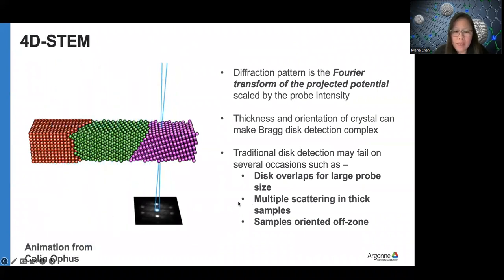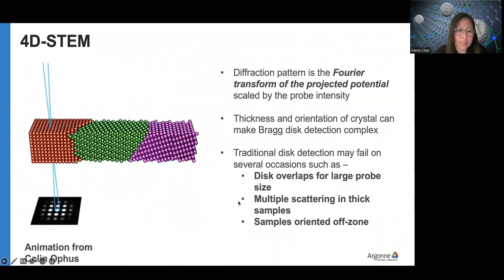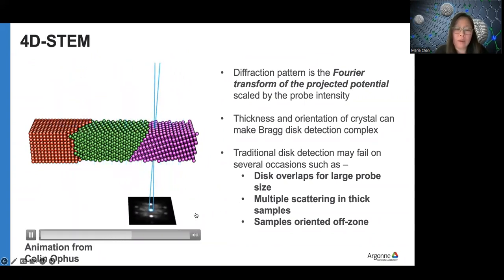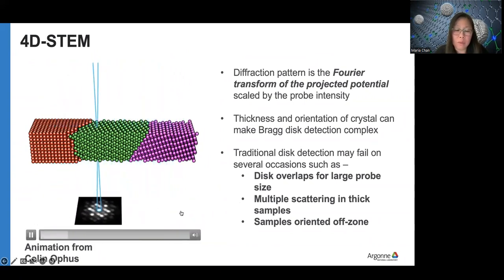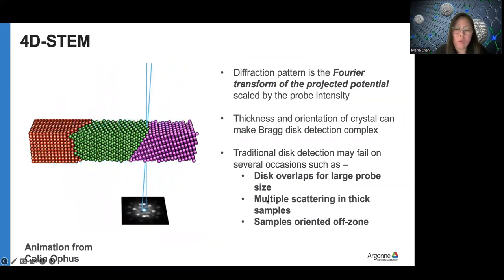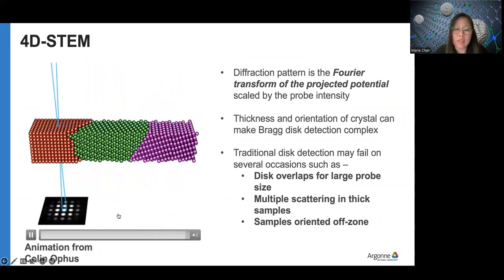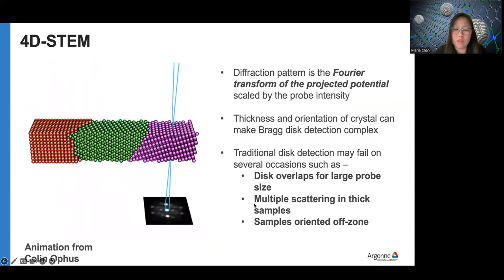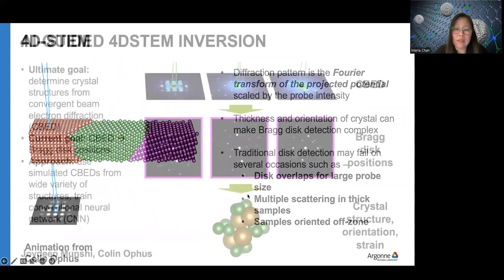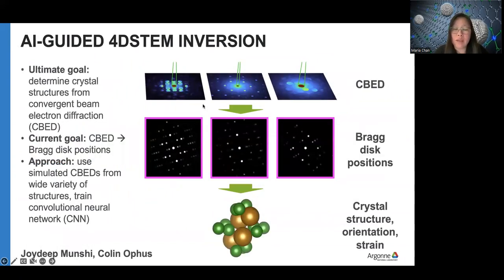It looks a little bit like a diffraction pattern as we are used to, but not exactly, because there is a thickness of a sample and multiple scattering, so it's not kinematic scattering unlike XRD. So what happens is some of those disks can be overlapped and sort of distorted. So one of the tasks that we first need is to turn those into Bragg positions and intensities, and then use that to try to invert and find the atomic structure, corresponding crystal structures and strains and so on.